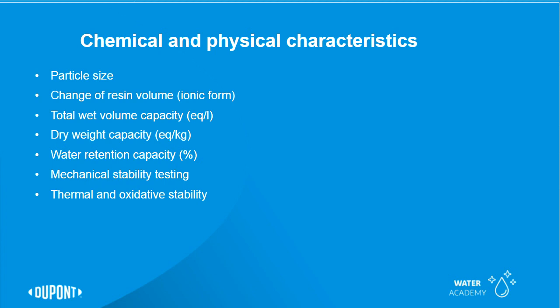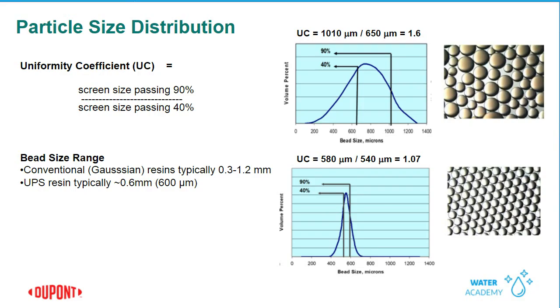I've mentioned Gaussian particle size distribution and uniform particle size distribution earlier in the webinar, and I just wanted to talk about how we measure the uniformity, and that's through a uniformity coefficient. And this is most of the time on the product data sheet. It's not all of the time on our product data sheets. We usually call out the resin as a Gaussian particle size in the description. However, if it's not in the description, you can tell by the uniformity coefficient.